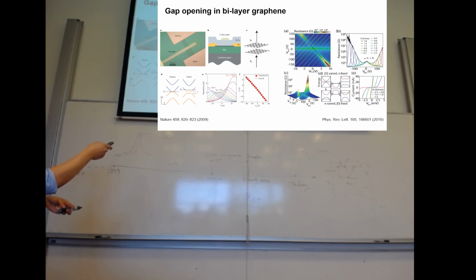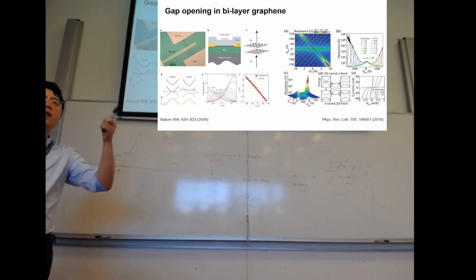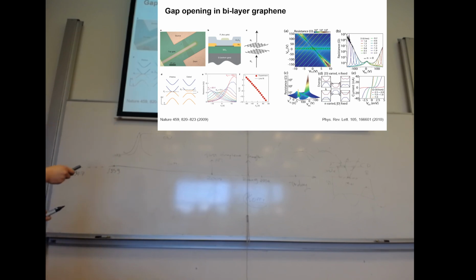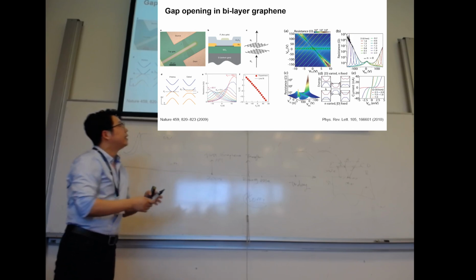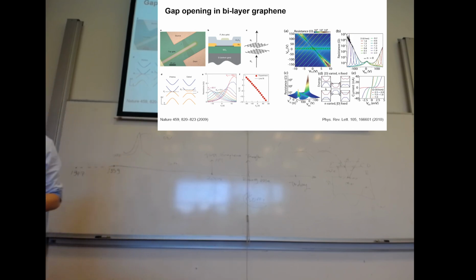So let's say this line, the black one, is charge neutrality. Every point on top of this black line is charge neutral. There are no electrons, there are no holes, and away from this point, up and down are electrical field pointing up and electrical field pointing down. With increasing the electrical field vertically, you have larger gaps, so it's always larger. And if you reverse the direction of the electrical field, it's vice versa.